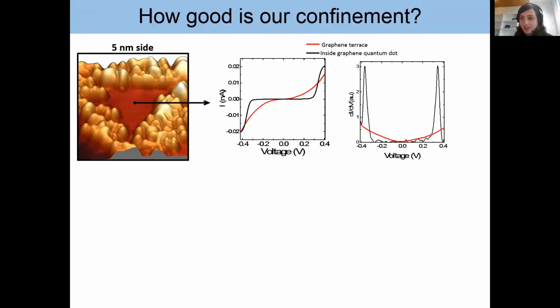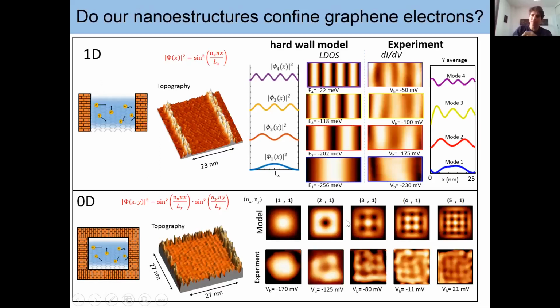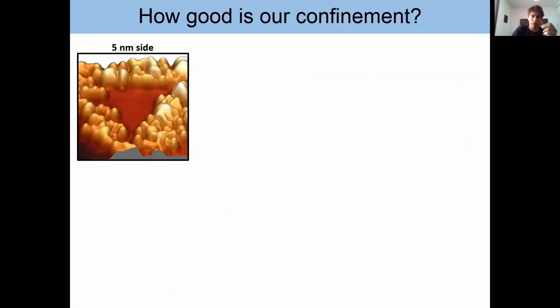Yeah, and then there's another question, which is, would you see effects of electron interaction in your ribbons? Yeah, the problem here again is that the manipulations are done at very high temperatures, and we have to measure at, for example, those measurements are done at 170 Kelvin, if I'm not wrong. So we are at very high temperatures. We would like to be able to measure the same system at 4 Kelvin, for example, and then to analyze with more care. And this is what we are trying now. We have built a new system where, in principle, we should be able to measure on exactly the same location at 4 Kelvin. So that's the kind of thing that we want to do. We have really a lot of ideas to work on here, but we would like to be at lower temperature.